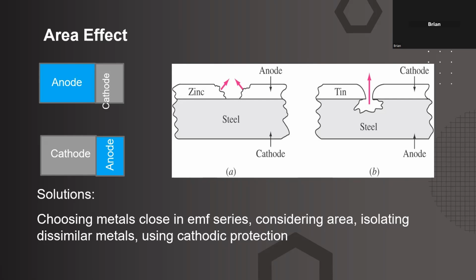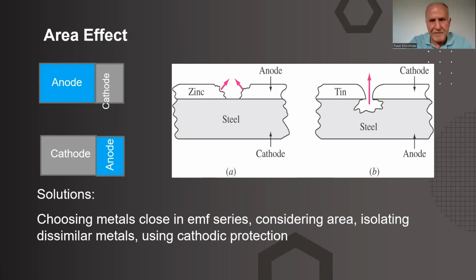So then do you prefer zinc coating or tin coating? It depends on the environment, indoor or outdoor. Gotcha. For example, the advantage of this one is that it protects steel very well. That's good. But the risk here is that if any scratch happens, then the whole steel, even in a very small area, will be susceptible to air. So this will be completely anode, a small anode with a big area of cathode, which causes very fast corrosion.